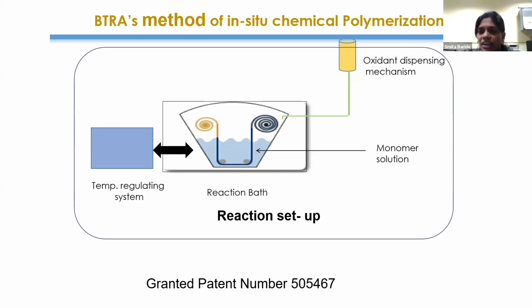As we have applied the jigger dyeing technique, we have already been granted a patent for this, because while carrying out the synthesis, we made modifications in the process in terms of temperature maintenance and so on. Temperature maintenance during synthesis is very important, because otherwise there are chances of side reactions. As I said, the chain continuity can be lost if the temperature is not controlled. So we did some setup by which the temperature is controlled, and for this we have already got the patent.